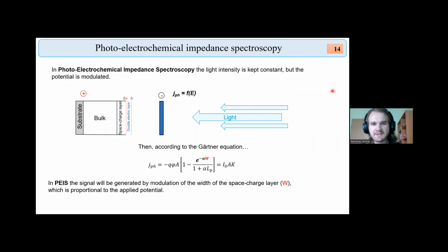Very briefly, I would like to talk instead of intensity modulated photocurrent spectroscopy, about photoelectrochemical impedance spectroscopy, which was more useful in characterizing these particular samples. So this is a very small modification of simple electrochemical impedance spectroscopy because the sample is illuminated. So if the sample is illuminated, then according to the Gartner equation, the photocurrent is decided by many variables, among which W, marked here W, is the width of the space charge layer. And the width of the space charge layer is proportional to the applied potential. So assuming everything else is held constant, that means the photocurrent will depend on the width of the space charge layer as we modulate the potential and keep the sample illuminated.